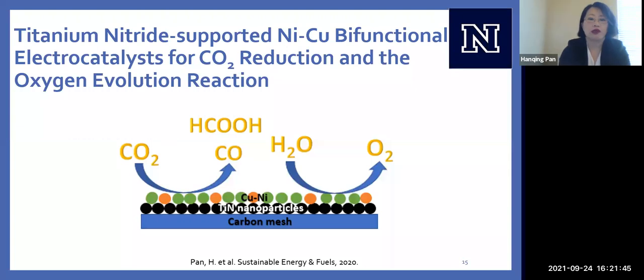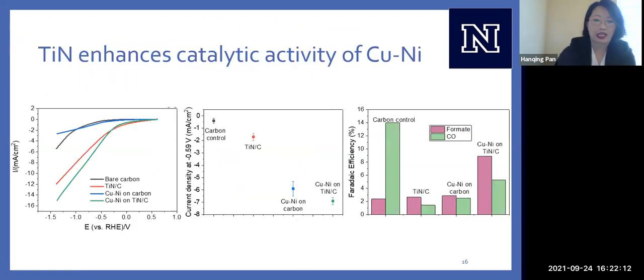So continuing with this nickel copper idea, we did one more study. Instead of copper oxide and nickel as different layers, we are co-depositing copper and nickel simultaneously at the same time on top of our carbon paper. But instead, let's add in an extra layer of titanium nitride nanoparticles. Because in literature, titanium nitride nanoparticles have been shown to enhance the catalytic efficiency of some of these metals. So we wanted to see if that worked.